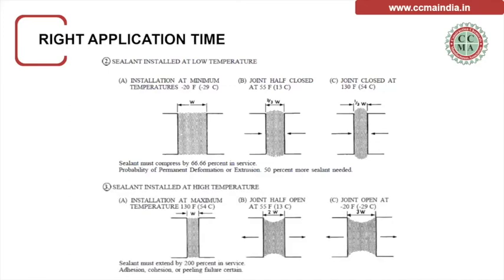Another scenario: if the sealant is applied at a very high temperature, at the time of application the width is W. When the temperature drops to 13 degrees Celsius, the width extends to twice, and when it further drops to minus 29 degrees Celsius, it has extended to thrice the original width. So the sealant is extending by 200% in service, and there will be sure failure due to adhesion and cohesion.